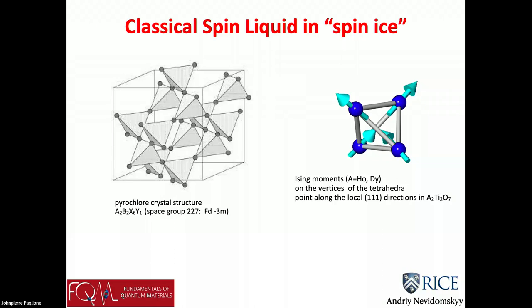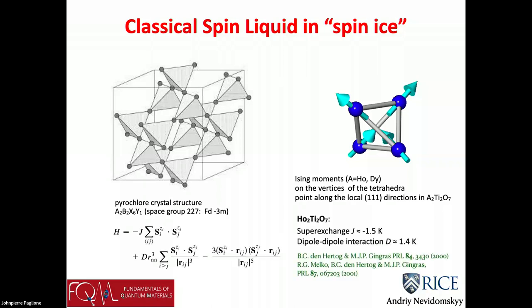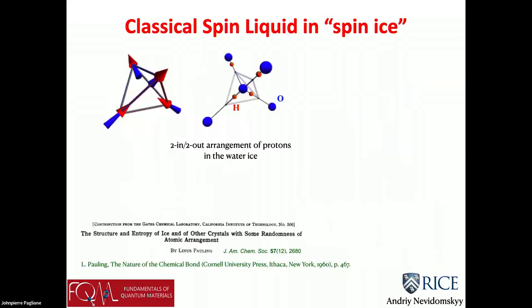Crucially, if you look overall, the system actually prefers to have overall ferromagnetic interactions. So this spin over here, even though it wants to point along its 1-1-1 direction, nevertheless wants to be, as much as it can, aligned with this spin over here. By the way, these interactions are a combination of superexchange and dipole-dipole interactions. It's not just nearest neighbors; dipole-dipole, of course, goes like 1/r³. So there are theories of what the model Hamiltonian should look like, but sweeping this a little bit under the rug, let me tell you why it's called spin ice.